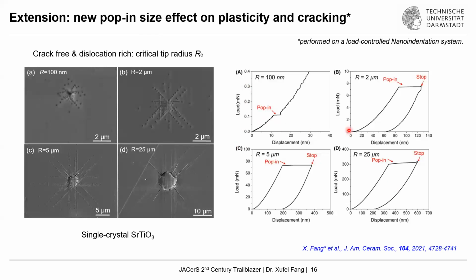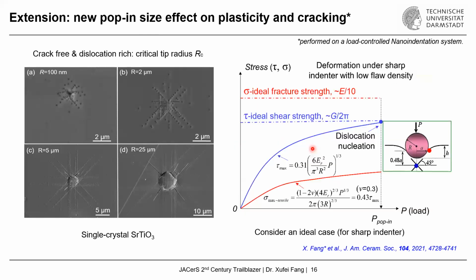So these are the corresponding load-displacement curves, and I will not go into the details, but rather show you the ideal case, meaning that we have a very sharp indenter, what would be happening underneath the indenter with respect to the stress level. Simply put, if we have a very sharp indenter probing a local region, we can assume that the local surface is almost perfect, meaning that there is no crack and there are no pre-existing dislocations. And based on contact mechanics, we can compute the maximum shear stress underneath the indenter. Very often it's happening in this region, as well as the maximum tensile stress happening here. We assume that the maximum shear stress is responsible for shearing the bonds, to break the bonds for dislocation nucleation, while the maximum tensile stress is responsible for breaking the bonds for creating cracks.